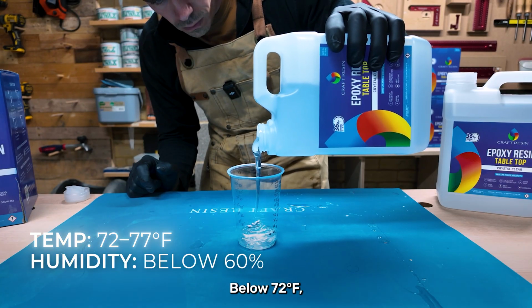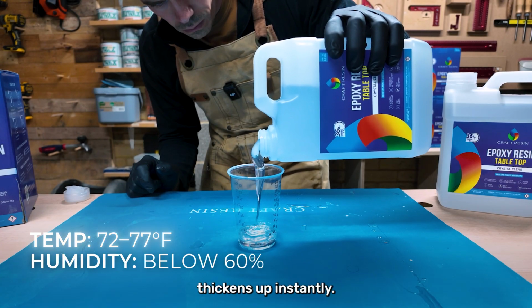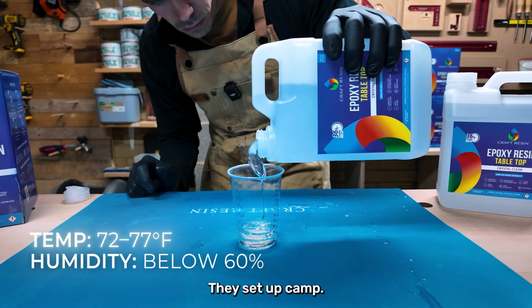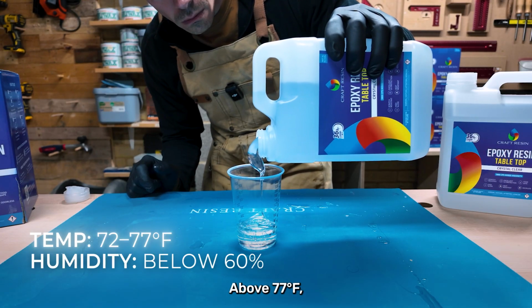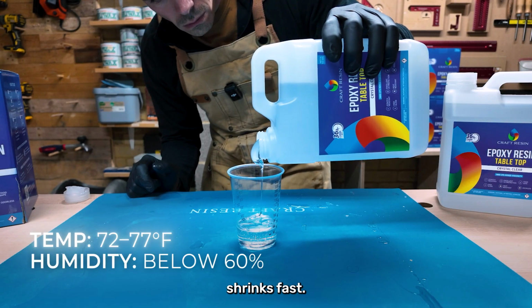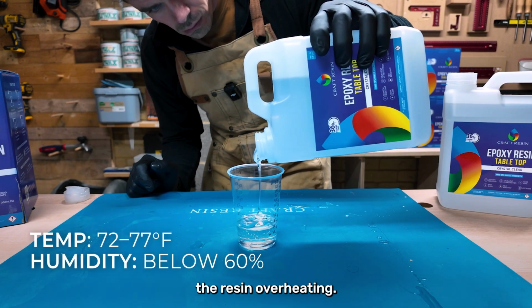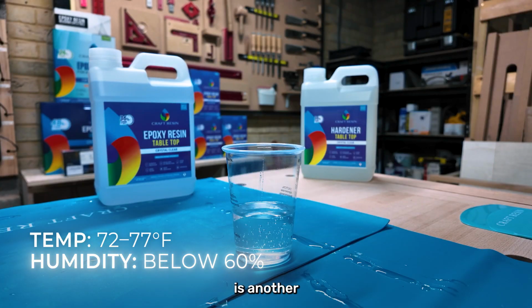Below 72 degrees Fahrenheit, the resin thickens up instantly. Bubbles get trapped and won't move. They set up camp. Above 77 degrees Fahrenheit, your working time shrinks fast. You also risk the resin overheating. Humidity is another silent trouble. Above 60%, moisture settles on the wet surface. This causes cloudiness or greasy spots.